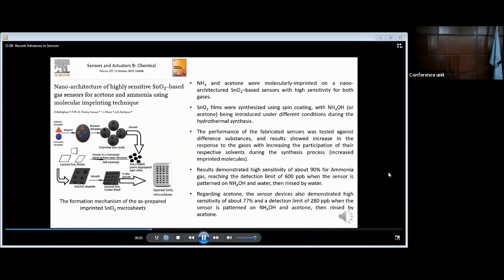Here is another interesting example of a gas sensor I would like to show you. In this study titled Nano Architecture of Highly Sensitive Tin Oxide-Based Gas Sensors for Acetone and Ammonia Using Molecular Imprinting Technique, the authors used the molecular imprinting technique by preparing a specific mold on the sensor substrate. They used acetone templates and ammonia templates, and so the sensor is ready to detect those two specific gases.